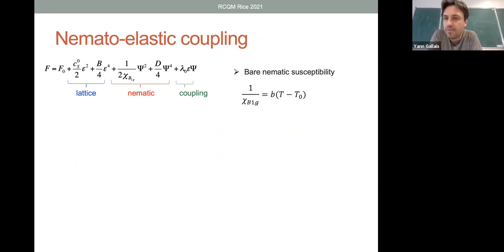So essentially, the difference between these two temperatures is an effect of the coupling to the lattice, what is known as nematic coupling. One way to think about it is to use the Landau free energy, where you would have epsilon, which is the lattice orthorhombicity, and psi, which is the nematic order parameter. And since they both belong to the B1G representation, they have a bilinear coupling. And this bilinear coupling is this last term, which has a coefficient lambda, which is often called the nematoelastic coupling.